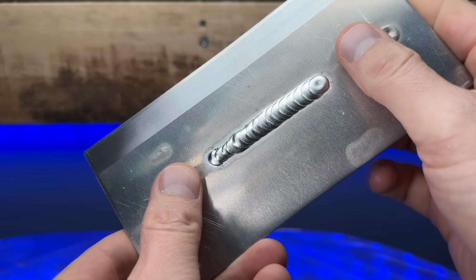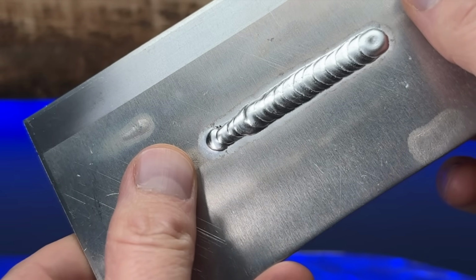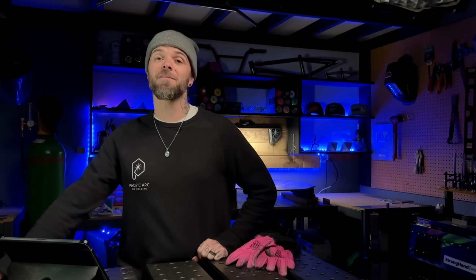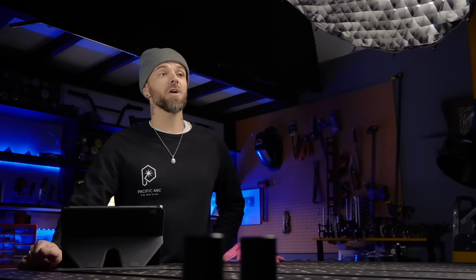But if you try and do a weld where the start isn't really established properly or everything hasn't quite developed before you start moving, or perhaps at the starting you have a little bit of an imbalance between the amount of filler material that you are using in relation to the material thickness or heat you are using, moving away from the start, continuing on with the full pass is going to be very hard to get things back under control. We want to make sure that we take the time and attention to focus on getting everything perfect at the start of every pass. But if everything's done perfectly at the start, by the time you start traveling, there should be nothing left to do except for just babysit.